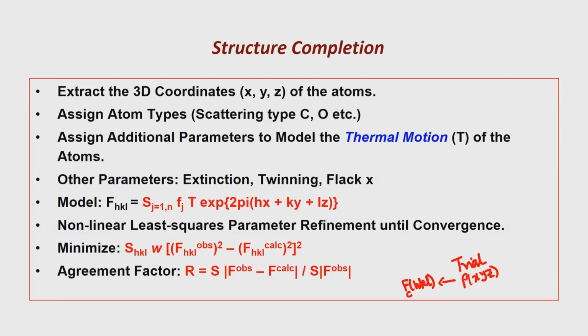So, that will be now the representation of whatever is left out, which is reserved for hydrogen atom positions. Or for that matter, if you have an atom which is wrongly put or wrongly introduced in this process, then it will also start showing up when you do a delta F based Fourier map. So, in the Fourier map, now you do not use F obs, you use delta F. So, when you calculate the Fourier map, you use delta F, and that means you will use whatever electron density is left out, and that is known as a difference Fourier plot, because we are taking the difference of the Fourier values of the observed and the calculated. So, therefore, it is a difference Fourier plot.